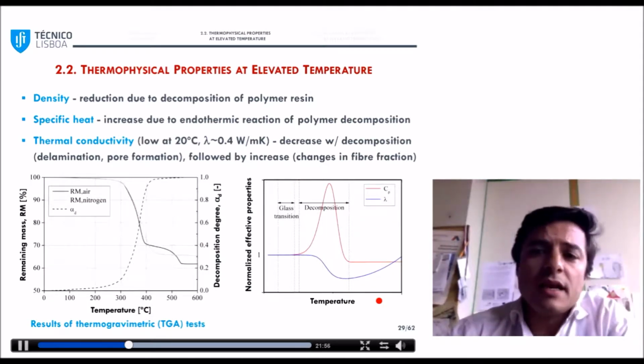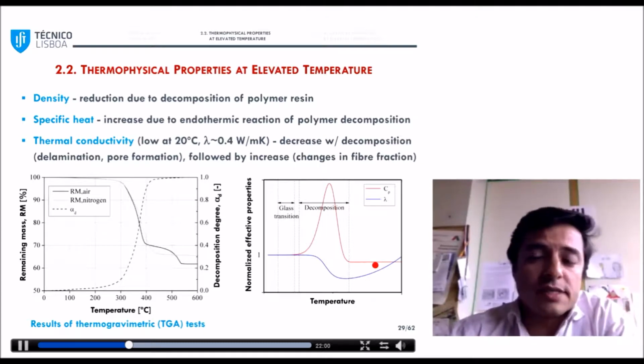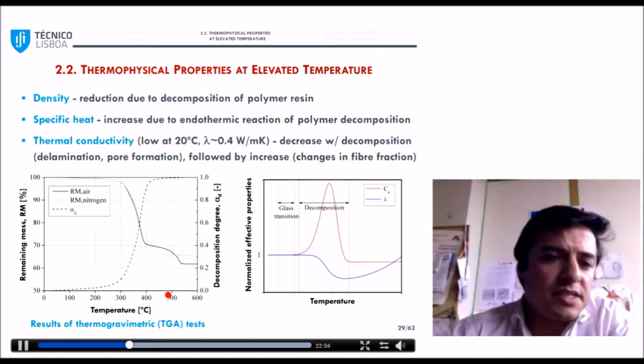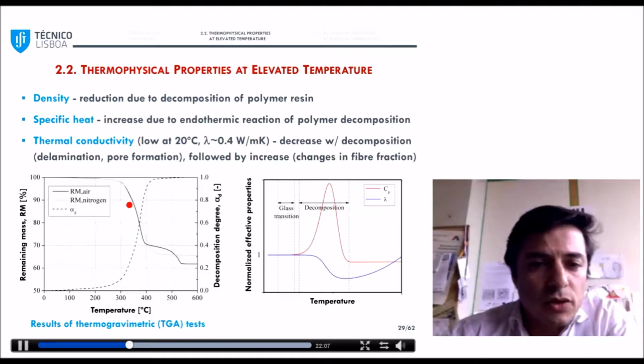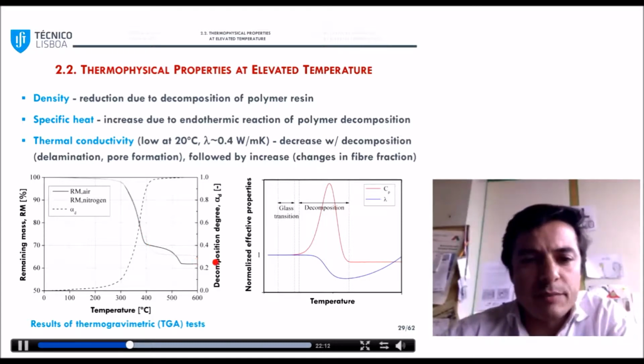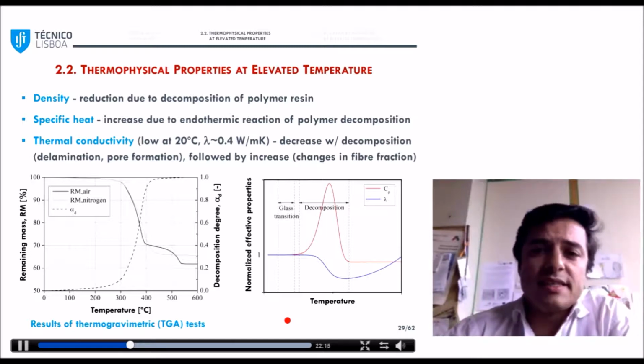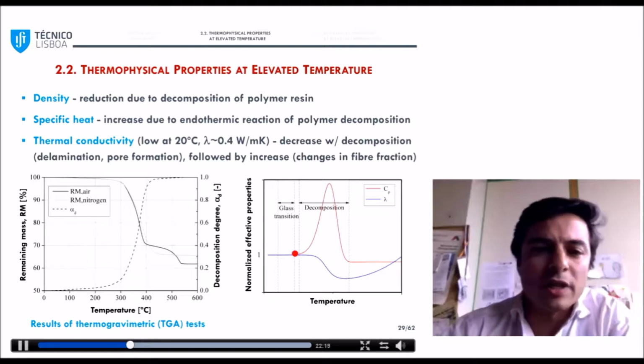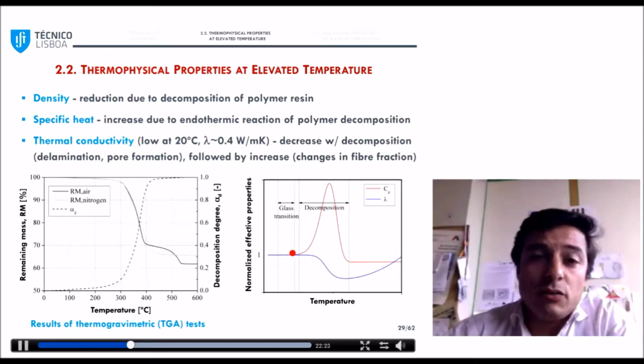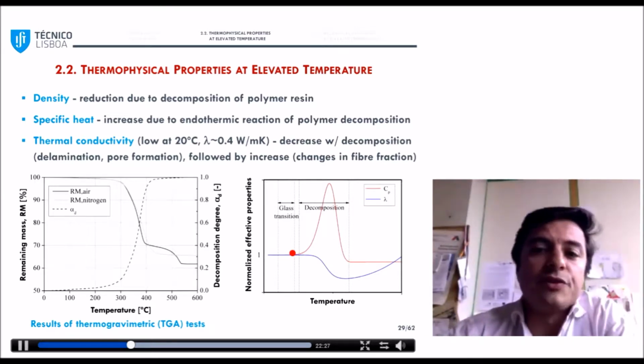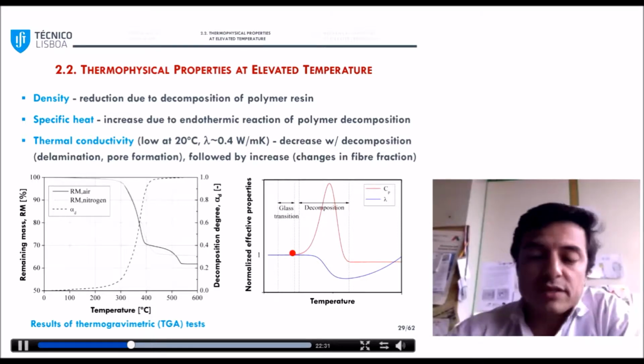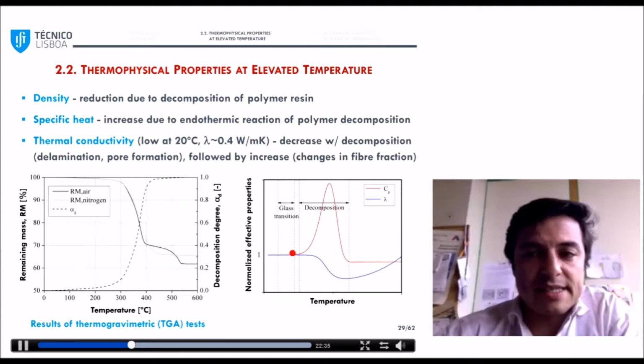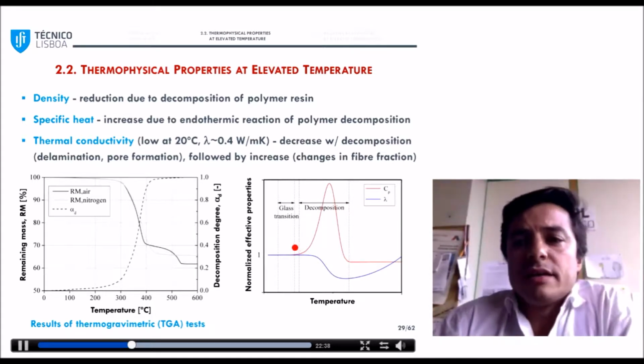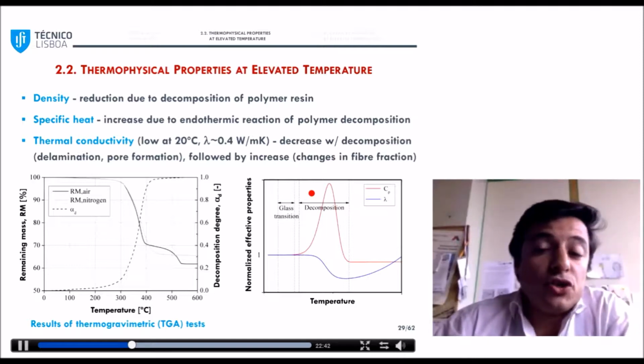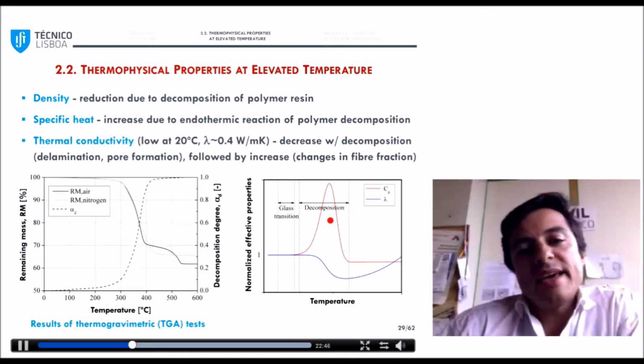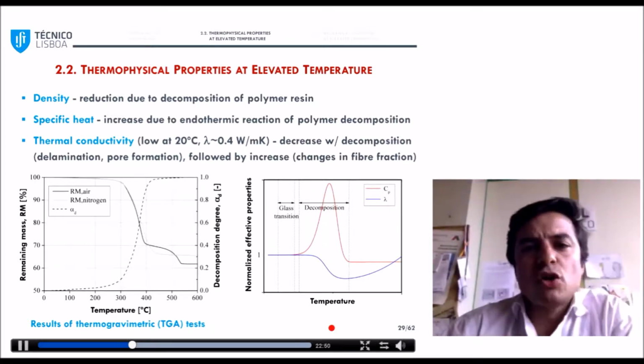So for the thermophysical properties, temperature, first of all, will cause a reduction of the density. You can see it here in this plot. These are results of TGA tests, so the density decreases with the temperature increase. Also the effective specific heat, which is this red curve in normalized values in this plot, is quite low at ambient temperature, and this is good because the material is insulating, it shows the insulation capacity of the material. So it first presents a peak. It increases significantly during the decomposition because this process is very endothermic, and then it decreases after this process.